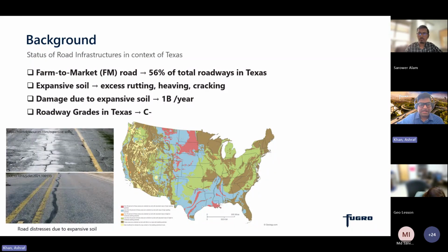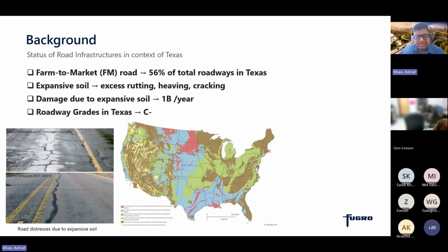So we know we are located in Texas, and we have a lot of issues with the expansive soil. Approximately 56% of the total roadways are farm to market road. And you can look at the map, most of the roadways are constructed over expansive subgrade soil. And if you look at the red zones in Texas, most of the major cities with densely populated areas are within this region. The presence of expansive soil amplified the pavement distresses, including rutting, heaving, cracking. So we are having lots of issues from the expansive soil, and the damage is around 1 billion per year, which is a huge amount.